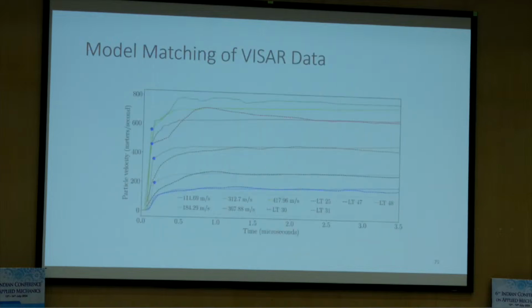And we performed all the tests and we matched the experiment. You can see that the dotted line is the experiment, and the solid line is the simulation. You see that it did well, but here it didn't do well. It's very complex because the viscous effects are dominating, and there's room to improve the model by introducing some viscosity parameters. So they all did well, relatively very well, because given the complexity of composite, you can't match exactly.